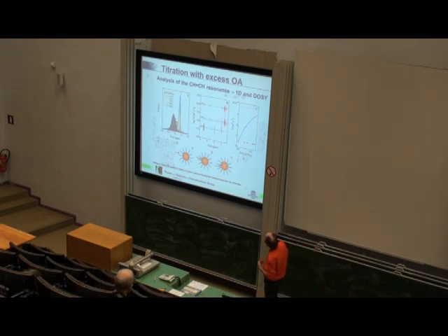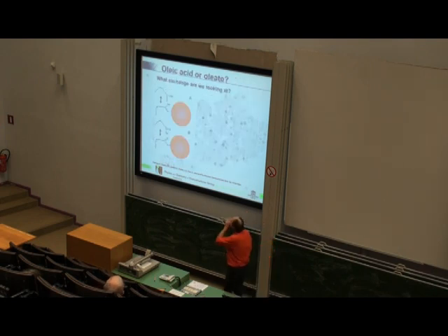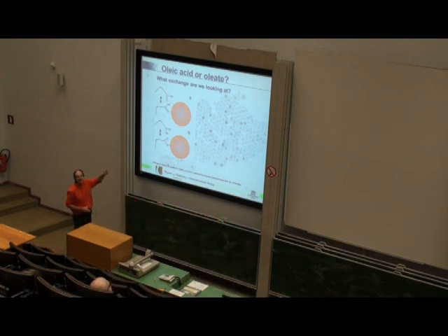And then there is a second step, a chemisorption, so we can remove an existing ligand and replace it by a new one. So there's a physisorption step, the first one, and a chemisorption step, the second one. And this is actually quite a nice observation, because by doing this, we can figure out what the bond is between this acid and the nanocrystal. In principle, there are two possibilities. This acid could just be bound to the nanocrystal as an acid with its carboxylic acid proton present, or it could be bound as an oleate, as an anionic species that has lost its proton.